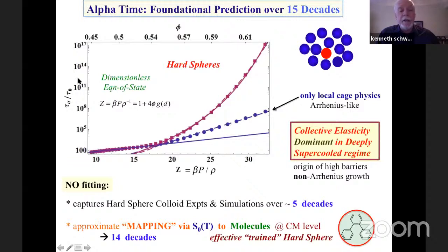Of course, we can calculate the alpha time for hard spheres. This is 15 orders of magnitude versus volume fraction or compressibility factor. The full ECNLE theory is this. If we turn off collective elasticity by hand, we get this blue behavior. And so this is a log linear plot with the compressibility factor. And so it essentially says that NLE theory is about non-cooperative hopping. This is an Arrhenius-like behavior, while all the non-Arrhenius part is coming from the collective elasticity.